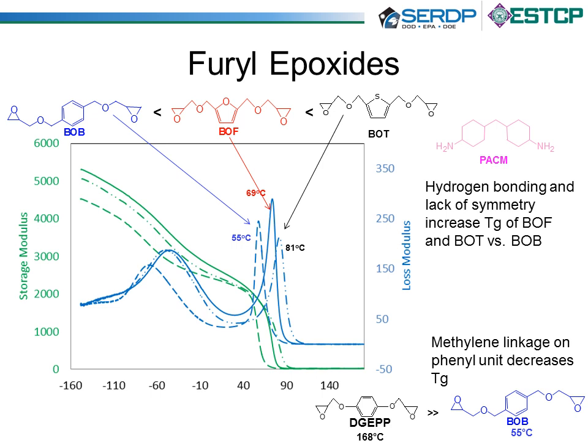One negative, however, is that there is a methylene spacer group between the furan group and the epoxide ring that detrimentally affects the properties. And we figured this out by looking at this DGEPP molecule versus that BOB molecule. When we cured those, the DGEPP had a much higher glass transition temperature because it didn't have that methylene spacer versus the BOB. So with furans, they're good, but we really need to figure out a way to reduce that methylene spacer to get to the high Tg.